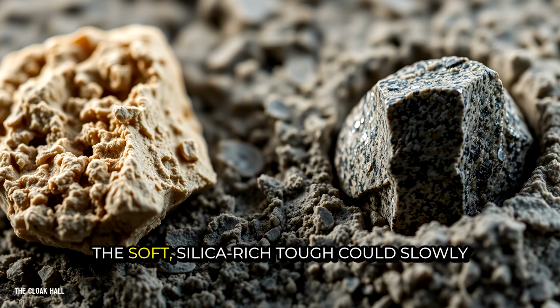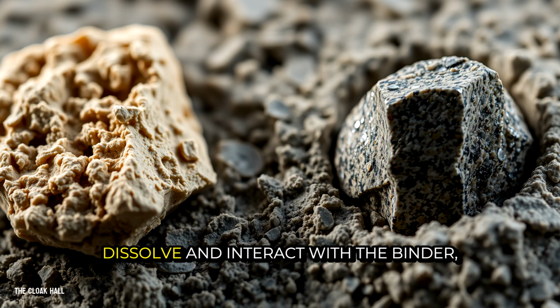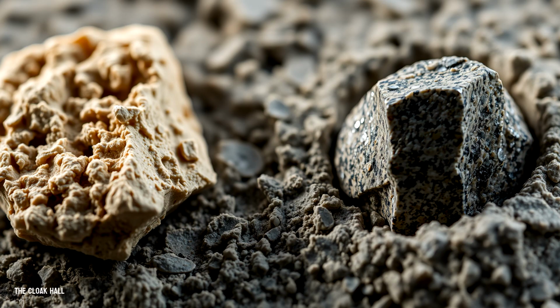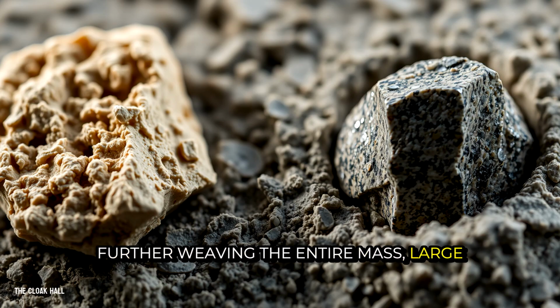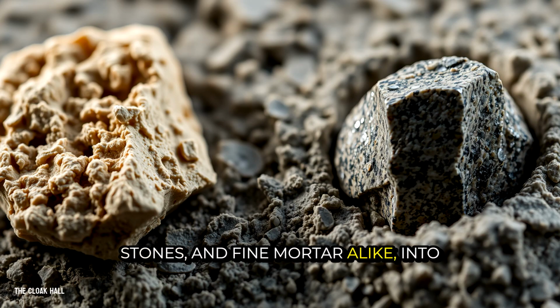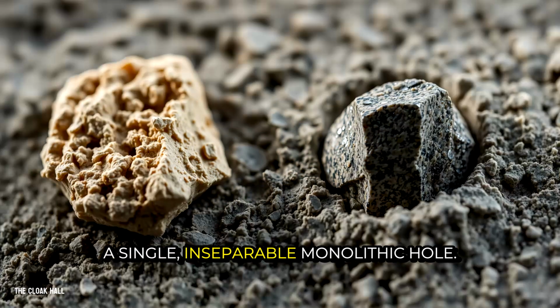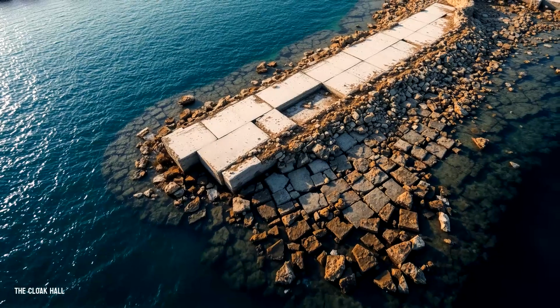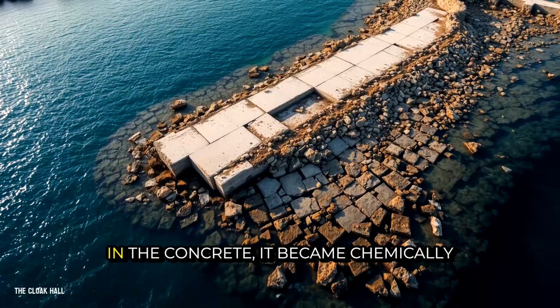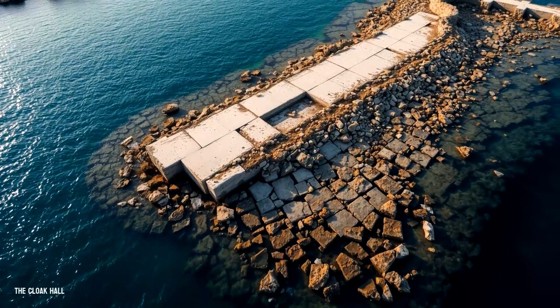The soft, silica-rich tuff could slowly dissolve and interact with the binder, further weaving the entire mass, large stones and fine mortar alike, into a single, inseparable, monolithic whole. The aggregate was not just trapped in the concrete, it became chemically married to it.